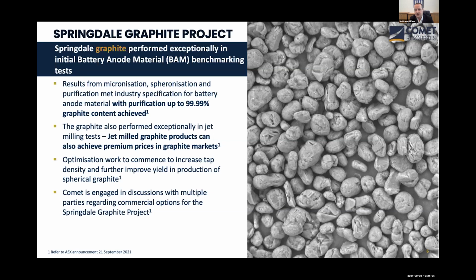Now, one of the big advantages for our project is that we start off with very, very small graphite. Two thirds of our graphite is roughly below around about 35 microns. And so, unsurprisingly, the material performed exceptionally well in micronization. It micronized easily and with low energy input. That's quite important because if you're starting with a larger flake of graphite and trying to micronize it down to the spec sizes that you need to commence spheronization, 15 to 20 microns, which is very small, it requires a lot of energy, because these graphite flakes self-lubricate basically as you're trying to micronize or grind them down to that size. And so having ours starting out at a very small flake size meant that it micronized very easily, very nicely, and with low energy inputs.